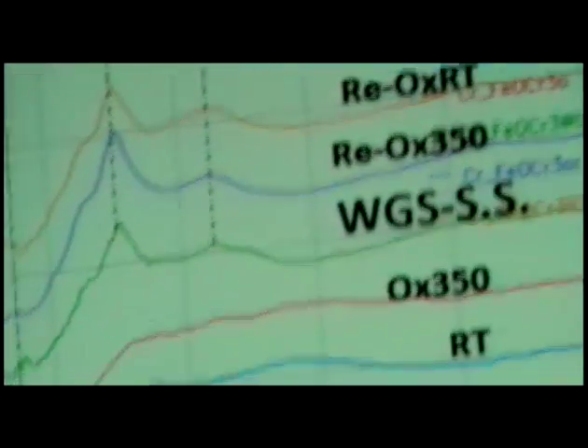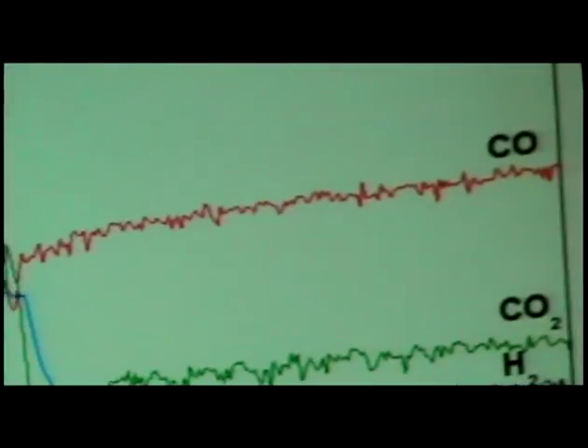Okay? And this is the catalyst oxidized at the reaction temperatures. The pre-edge is still there. From the water gas shift, the pre-edge is almost gone. We see new features appearing. These new features are of chromium 3 oxide. So we've reduced chromium 6, we start seeing chromium 3.